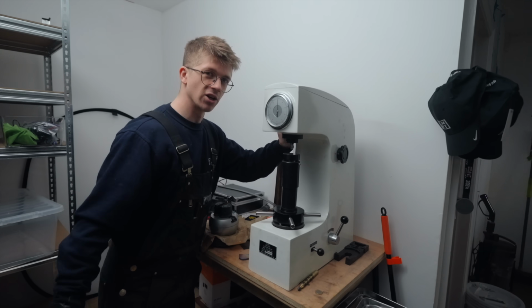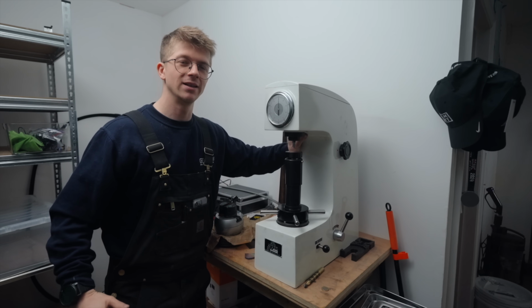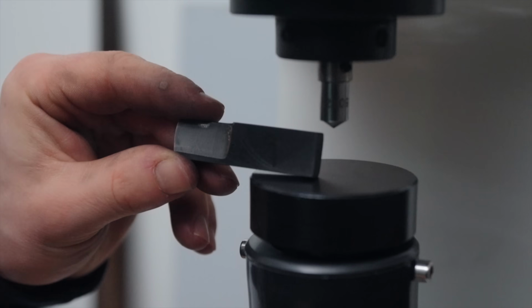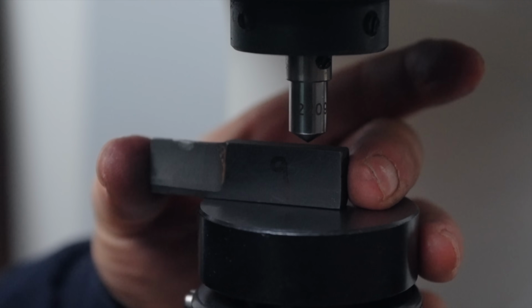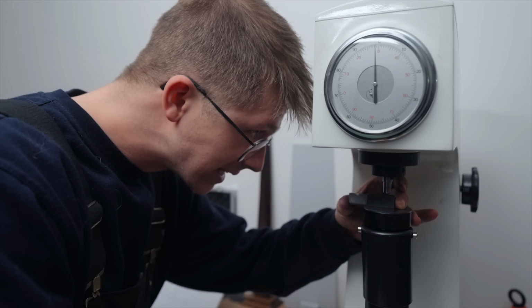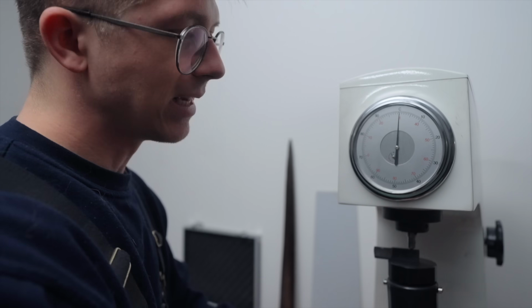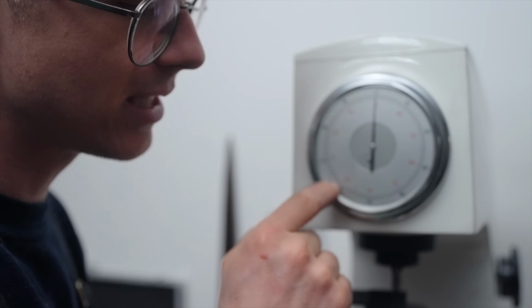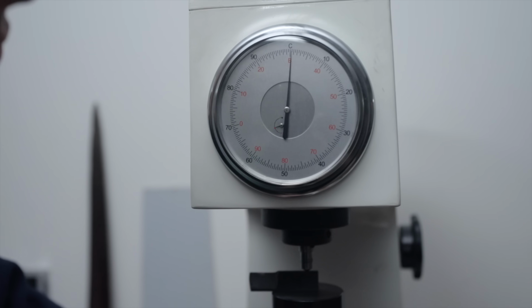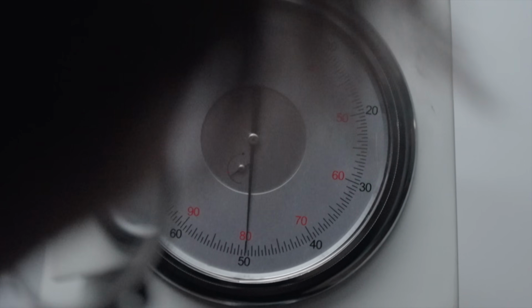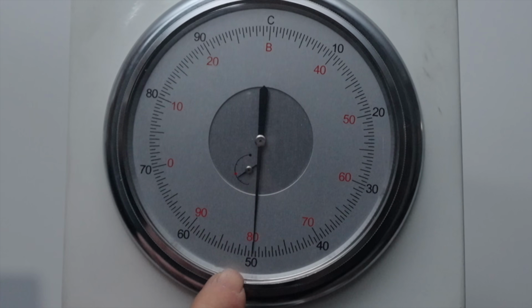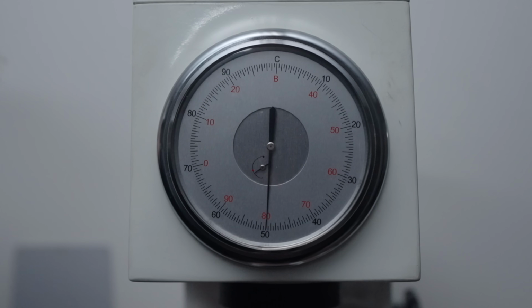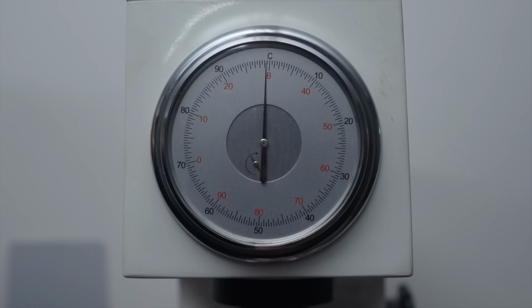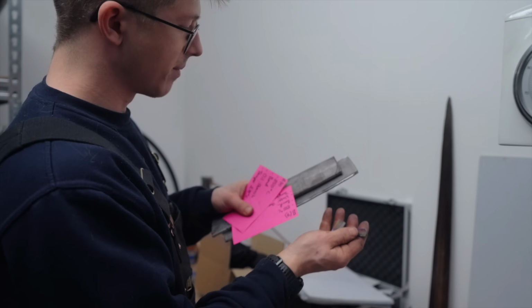Righto, this is our new Rockwell hardness tester. This is sample 9 from the last set of experiments, so this is just 1080 steel that's been hardened. What I expect from hardened 1080 for it to be suitable for a knife is something in the region of 60 Rockwell C. 1, 2, 3. Bring that forward. That's actually a little bit softer than I expected. 50 Rockwell C. So perhaps we tempered it a little bit hotter than we normally would. We're gonna run a number of these experiments across all our samples, get the averages, and see what sense we can make from the numbers.